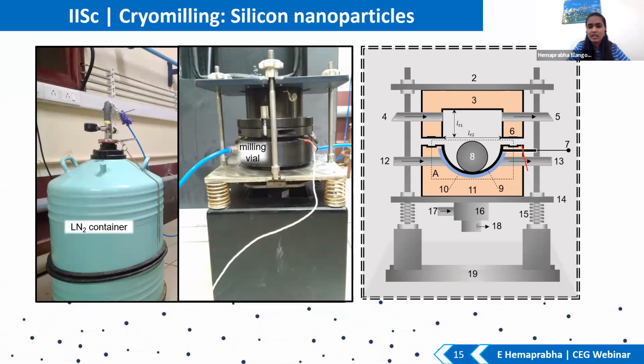But then, for example, this is the schematic of it. I have a ball here and I have a cup here. If I put bigger pieces of silicon at that temperature, under this pressure, where we give a pressure here so that the ball will move up and down, we will get the bigger silicon particles crushed into nanoparticles. We were putting the bigger silicon particles here, and once we give the pressure, we were getting the silicon nanoparticles. That much we were sure.